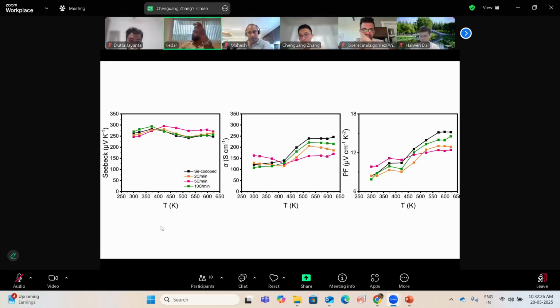I think you should do it. I think Jayanta is also learning PPMS, so it might be useful. Pawan will be around. You can basically make the full contacts and load. The low temperature resistivity curve is an indirect indication of ordering. So you could maybe say at 2% cadmium, we already have ordering or less ordered domains. That's also interesting.